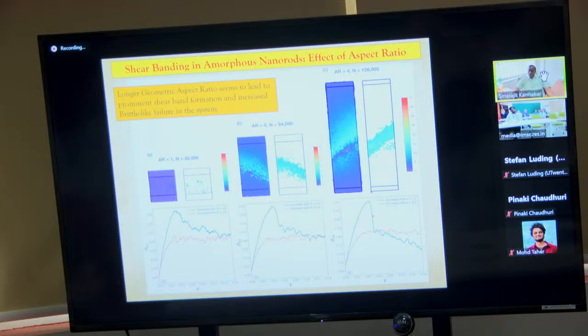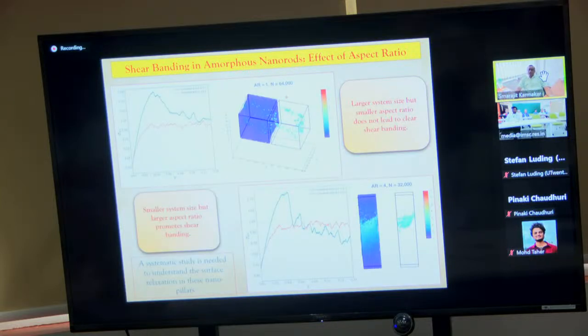If you look at the corresponding stress-strain curve, you see a very sharp drop. It suggests that along with the annealing protocol, as you go to an open geometry scenario, your sample geometry starts to matter for stability. To stress the geometry, we looked not at the sample size alone. We looked at a bigger system of 64,000 particles, but in a cubic shape, and you see that there is no shear band. But with a smaller system of 32,000 particles and an aspect ratio of 4, you get a very clean shear band.